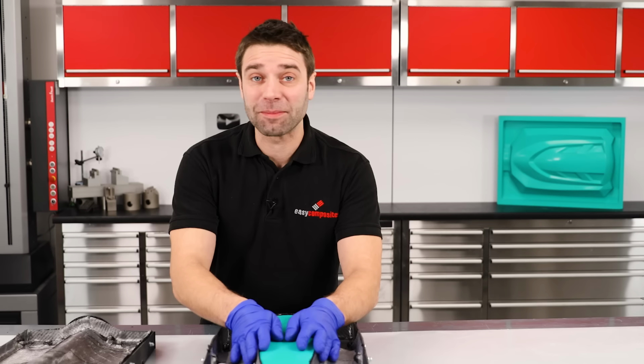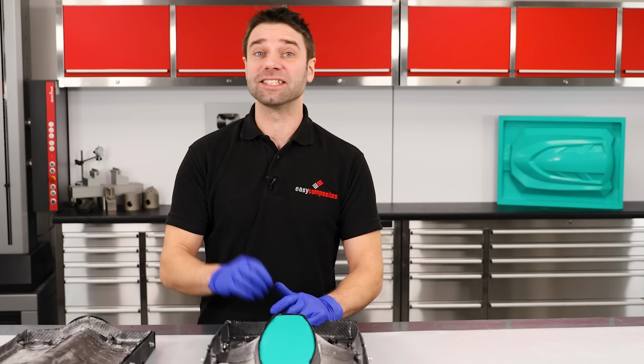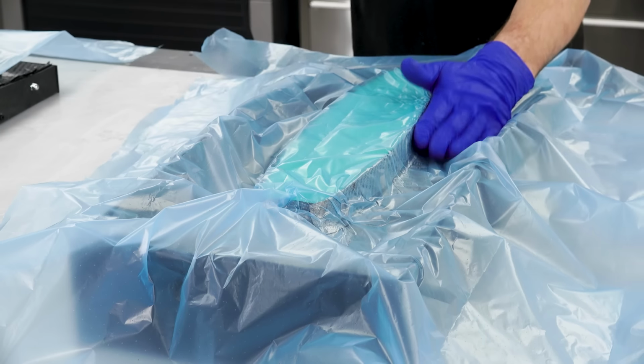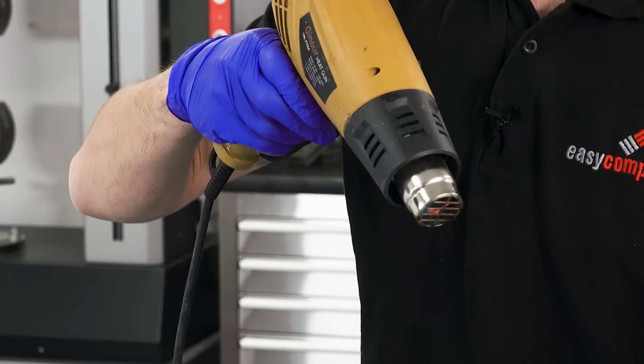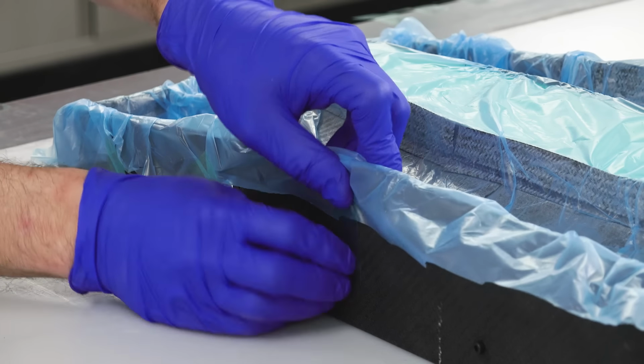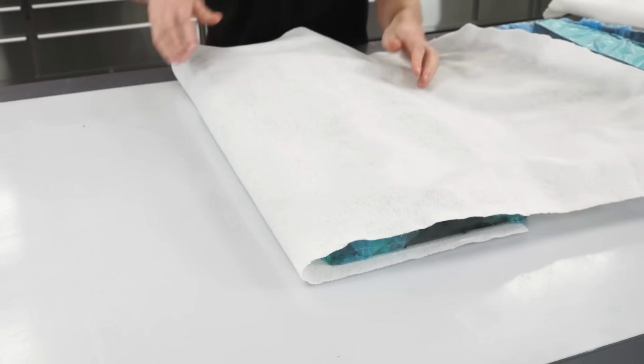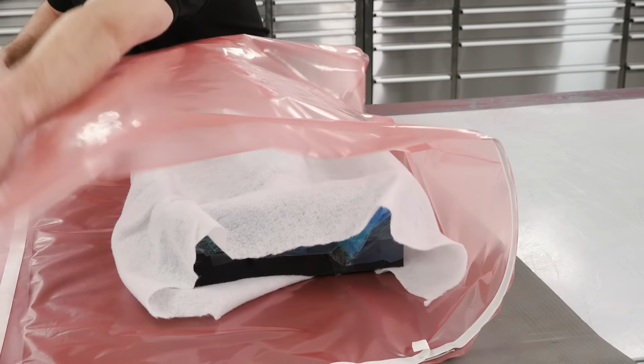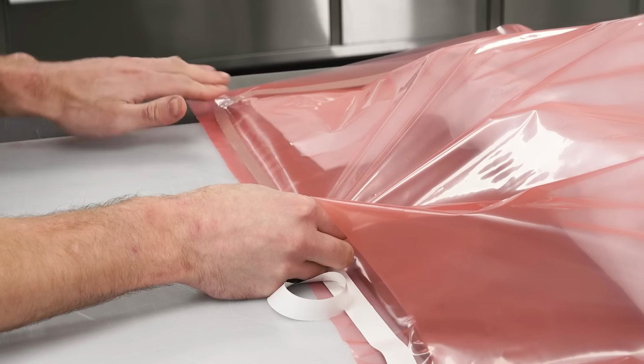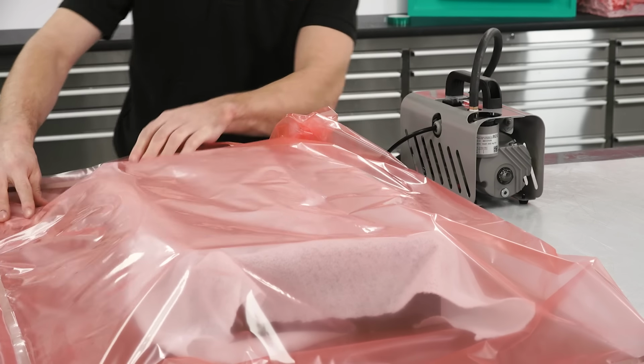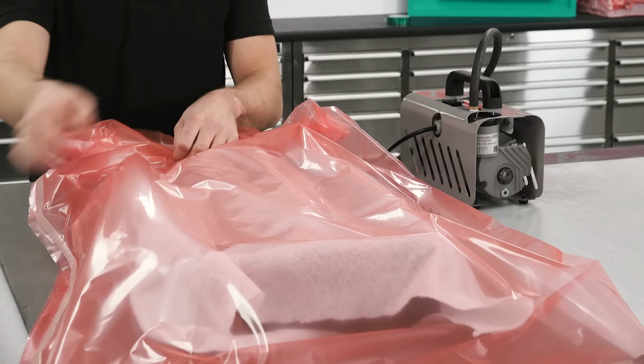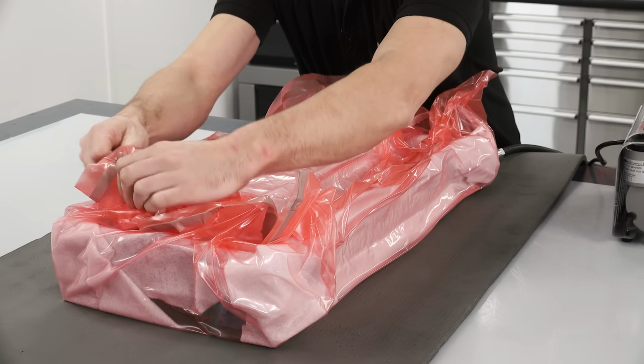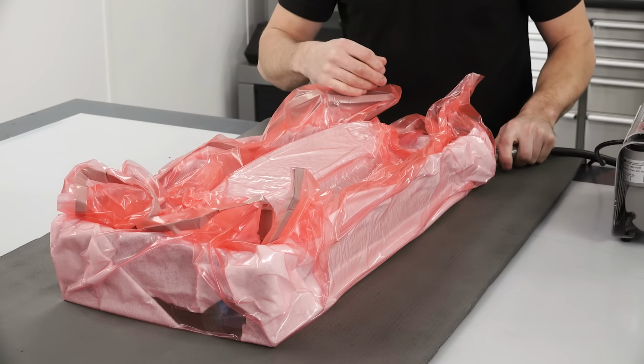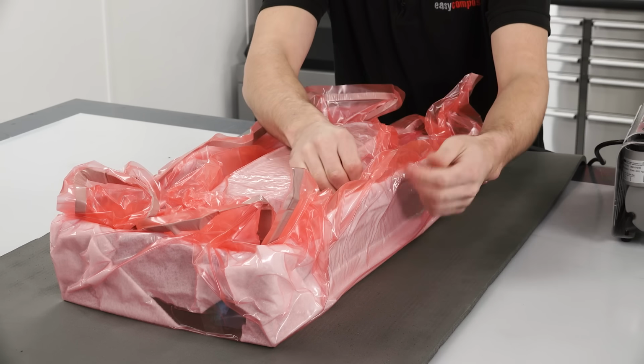Now that we have these parts laminated, we can get on and vacuum bag these and put them in for cure. A perforated release film is added, followed by a breather and then a vacuum bag. Full vacuum is then gradually pulled with careful manipulation of the bag to avoid any bridging. Wherever you have the pins, do pay particular attention as they will need a good amount of extra bag to fully surround them without risking puncturing the film.